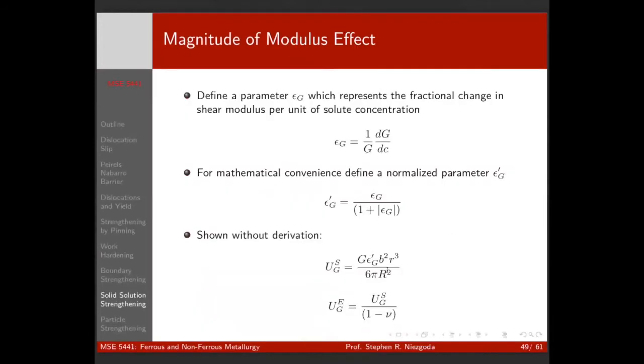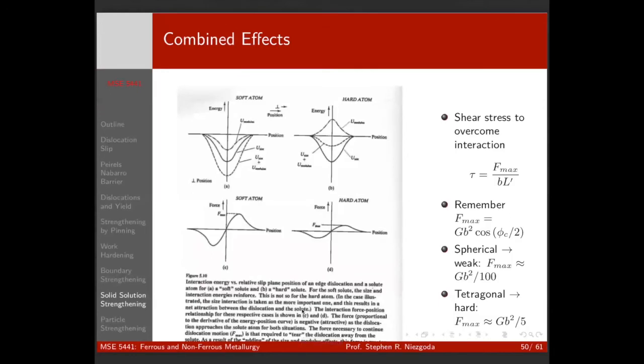Right, but the magnitude of it is basically going to be a strain-like term, which gives you the change in shear modulus per unit of solute concentration. So this is a dimensionless term that is like strain. And it's going to be proportional to that, and the Burgers vector squared, and the radius, and the distance squared. So it's a 1 over r squared term. So it's a much shorter range effect than the size, right? And it's always going to be combined rather than destructive, right?